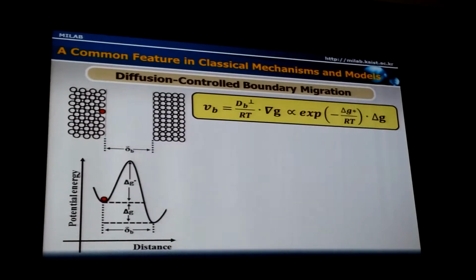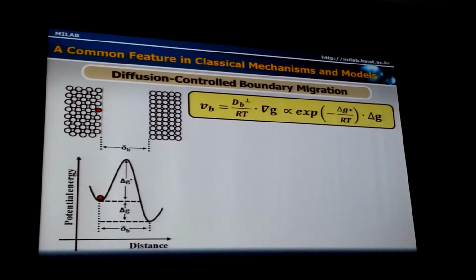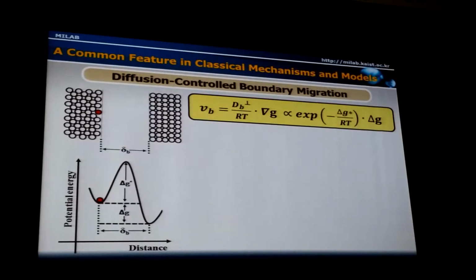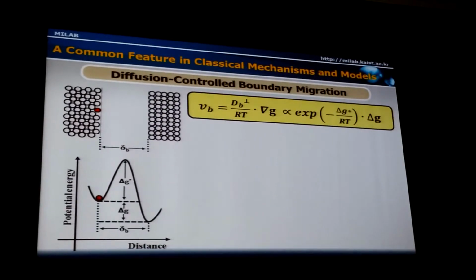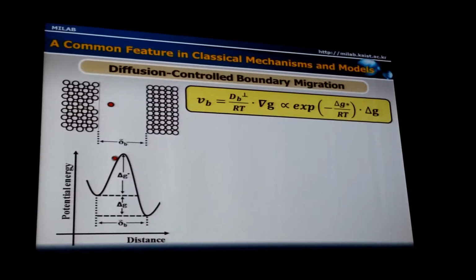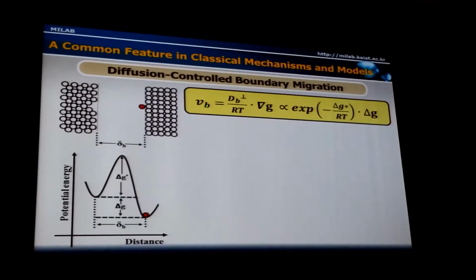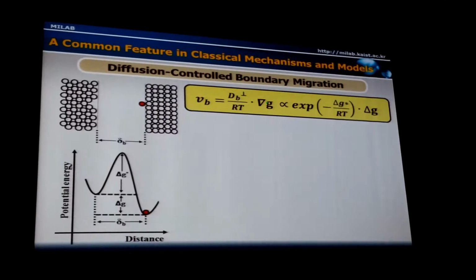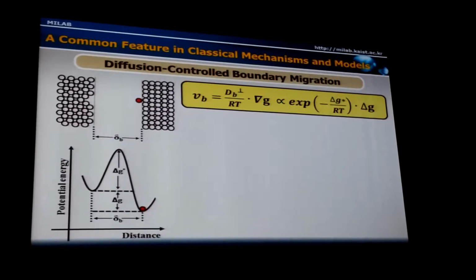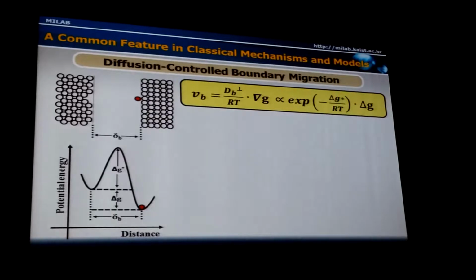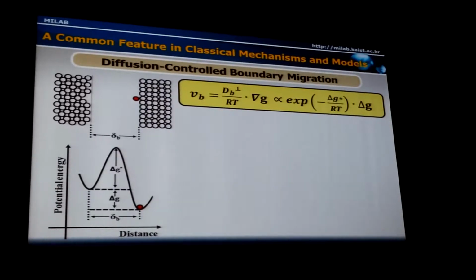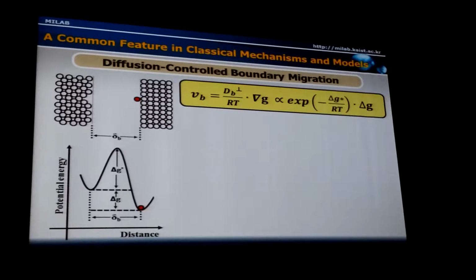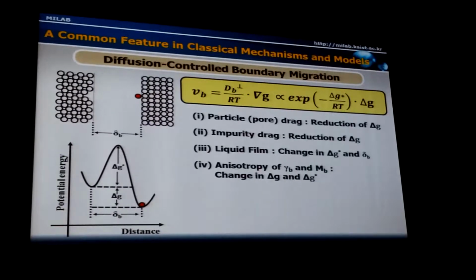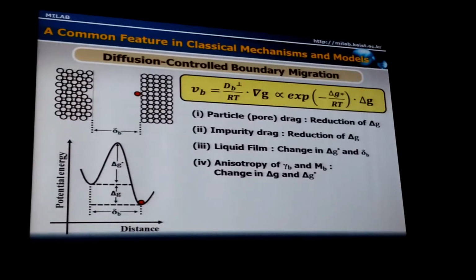One of the common features in the classical mechanisms and models is that all the processes were assumed to be governed by the diffusion of atoms across the boundary. So boundary migration velocity, boundary velocity, is expressed by the mobility of the boundary and the chemical potential gradient. And the mobility is expressed by an exponential function of the activation energy and the driving force. And this holds even in the presence of second phase particles, impurities and liquid films.